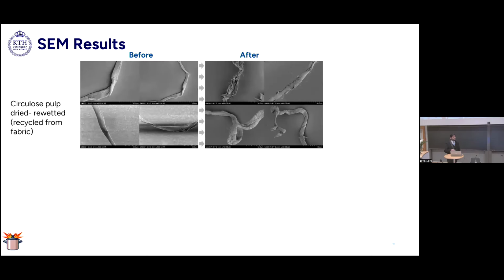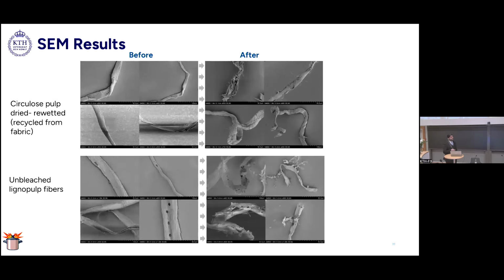In the case of Circulose pulp, we have seen a little bit of surface fibrillation, exactly similar to what we saw in the never-dried dissolving pulp. And in the case of the unbleached lignocellulose fibers, we saw the most surface fibrillation. Again, this is very intuitive since you have a fiber which has lignin, which is readily removable at higher temperatures. Also, when you remove the lignin and the hemicellulose, you have a lot more accessible surface area of the fiber for steam to do the pretreatment and break down the fiber.